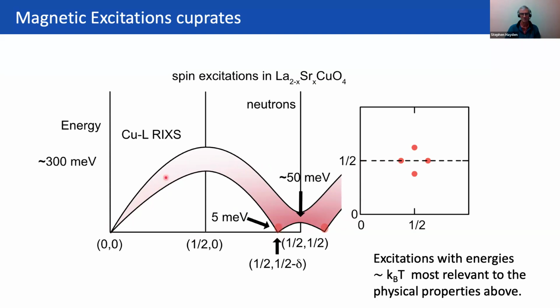So one gets a sort of broad set of excitations here going up to about 300 meV in doped materials. These are seen in RIXS, and then neutron scattering measures around a half, pi, where the excitations become stronger and they dip down again. And we have a lot of spectral weight here, which we believe might cause the pairing. We have the so-called hourglass. And I'll show you in a minute, there's some stuff that is peaked at about 50 meV. If we just look at this region here, there's another contribution which goes down to the lowest energies, which is what I'm going to talk about today. So it's this little blob on the end of the tail.